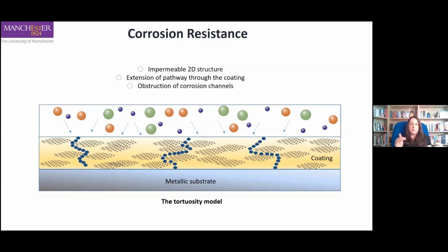So the mechanism for anti-corrosion with graphene is fairly well understood. If you look at the diagram here, essentially graphene in the coating extends the path length of corrosive media or the electrolyte down through the coating to the metal underneath. And through the coating, the way the graphene layers are positioned stops those ions or those molecules having a direct route through to the surface. And we tend to refer to that as the tortuous path analogy, which you may have come across many times.